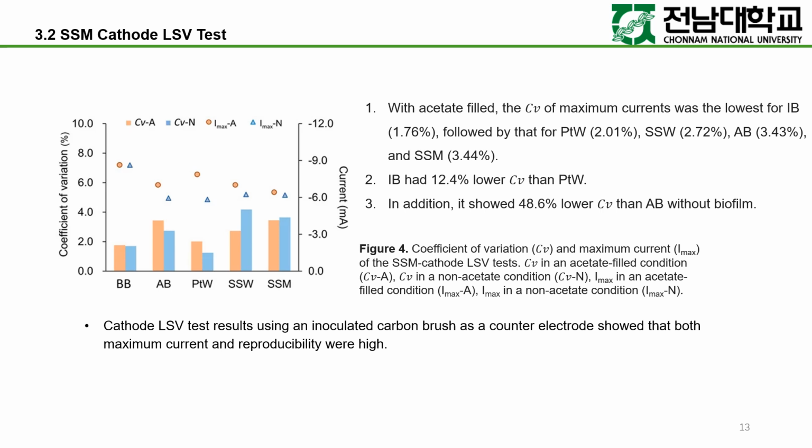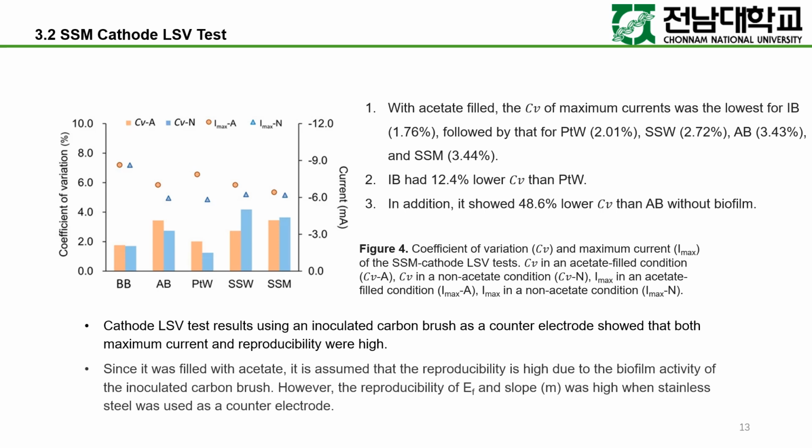With acetate filled, cathode LSV test results using an inoculated carbon brush as a counter-electrode showed that both maximum current and reproducibility were high. In addition, since it was filled with acetate, it is assumed that the reproducibility is high due to the biofilm activity of the inoculated carbon brush. However, the reproducibility of EF and slope was high when stainless steel was used as a counter-electrode.